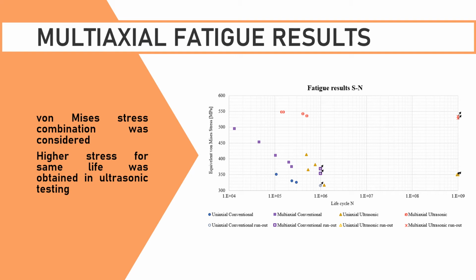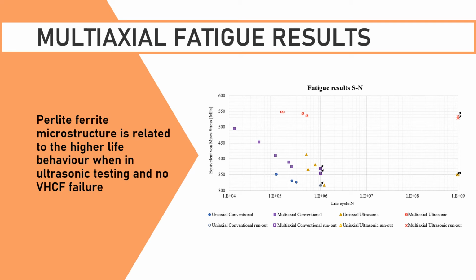After machining several specimens, both multi-axial tension torsion specimens and uniaxial tension compression specimens, they were tested in fatigue and then compared with conventional tests with the same stress cycles. Observing the results, we can see that ultrasonic fatigue results do increase the life, or for the same life we have higher stress. From the literature and from comparing different results of different studies, we concluded the reason for this higher stress for the same life was related to the pearlite ferrite microstructure, which increases such stress, but it also prevents the failure in a very high cycle fatigue region.